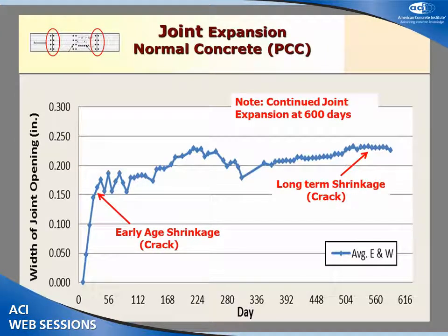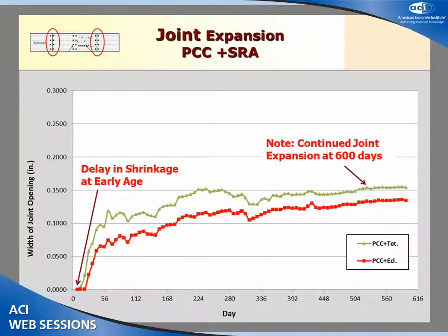This graph shows the joint opening, joint expansion for the normal concrete. As you can see, the shrinkage starts at early age for Portland cement concrete, and this shrinkage or expansion continues for a long term. We measured this for about 600 days, and we still noticed the joint expansion continue after about 2 years.